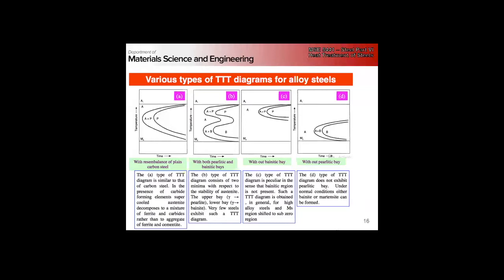And then we have what are called the steels that exhibit the pearlitic and bainitic phase, where our bainite is pushed forward, and these are referred to as bays. So in this case, we can get down, we'll talk about austempering, where we come down here, quickly quench to some temperature above the martensite start, and then come in to get a lower bainite temperature, right?